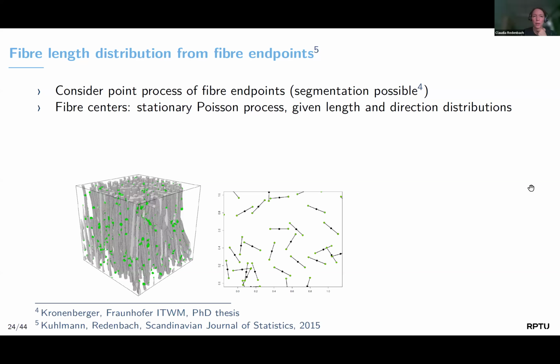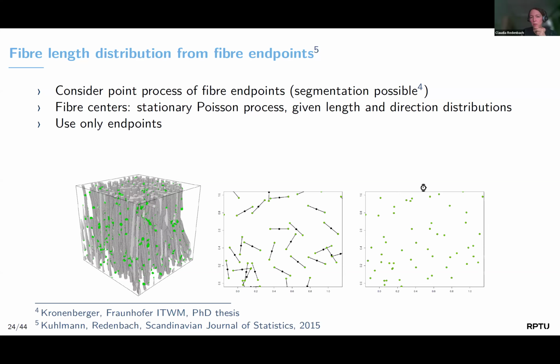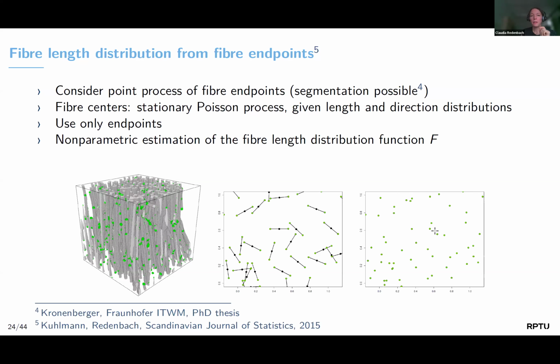Namely, if we assume that the fiber center point is a stationary Poisson process, which basically implies that the centers are thrown independently of each other with a given length and a given direction distribution, then we can use the fact that if we just look at the endpoints, so just these points shown here, without taking into account how the fibers were initially collected, then we can get a non-parametric estimation of the fiber length distribution.